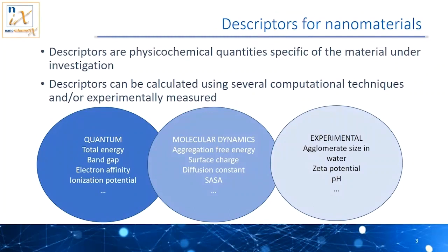force field molecular dynamics. Some descriptors are measured experimentally, such as zeta potential, which is the potential difference between the dispersion of the colloidal suspension and the stationary layer of fluid attached to the particle. Zeta potential is related to the stability of the colloidal suspensions and is estimated experimentally through electrophoresis or calculated using